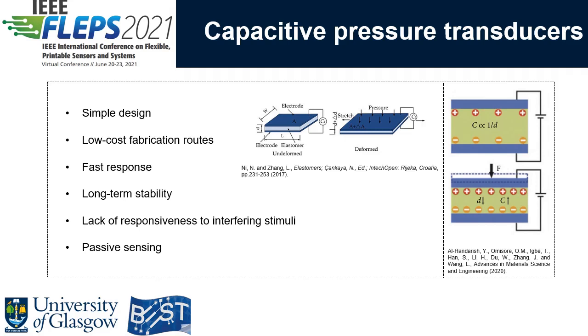On the other hand, this silicone-based polymer has an elastic modulus of 1 megapascal, which means PDMS-based capacitive sensors will experience small deformations under pressure and hence will have limited sensitivity range. Different material design strategies have been investigated to expand the detection range and improve sensitivity in PDMS-based capacitive sensors.